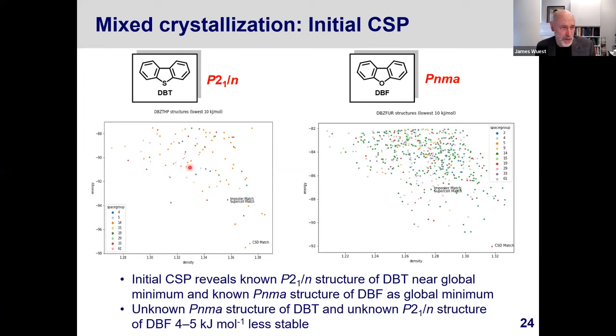This is not the finished work, but you can see here on the left the predicted structures for the thiophene. The P2₁/n structure turns up in the search. It is not the global minimum. There's another structure here that we have never seen, even after looking at this quite a bit. I don't know whether this is a real structure or not, but at any rate, it's there. And the same thing is essentially true for the dibenzothiophene structure. There's a match with the observed reported structure, which also turns out to be the global minimum.